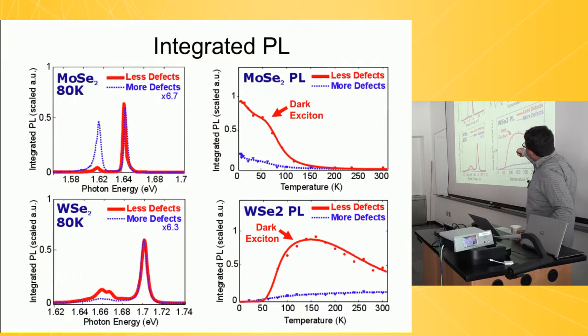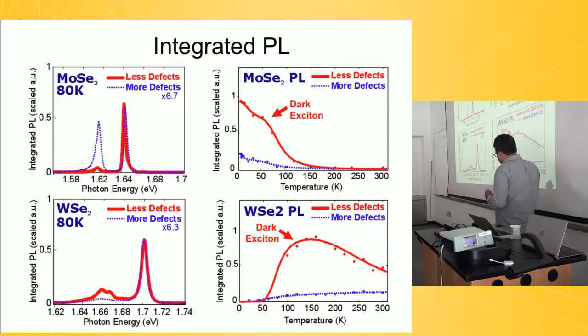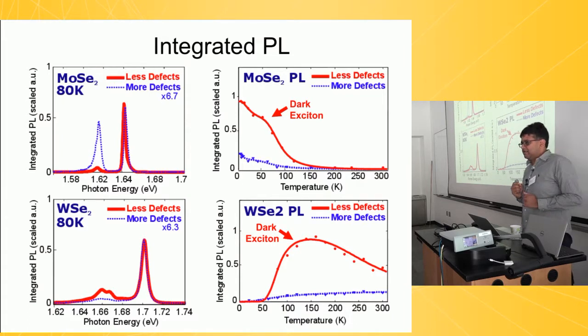So here's the data. What we do is we measure the photoluminescence. So here's the photoluminescence response of molybdenum diselenide and tungsten diselenide, and we measure this as a function of temperature. And in moly diselenide, as you expect, it goes up with decreasing temperature. And in tungsten diselenide, only in the clean crystals, we see this physics. So in the cleanest crystals, the photoluminescence abruptly drops off exponentially at low temperature. In a dirty crystal, you see this overall behavior that comes from the fact that there's just a huge number of events where electrons from one valley are being scattered into the other valley.